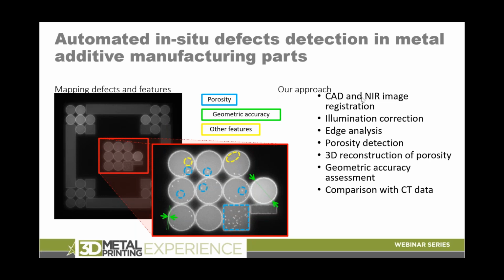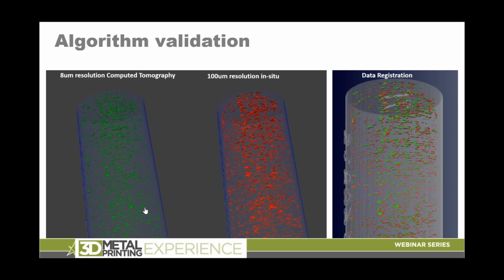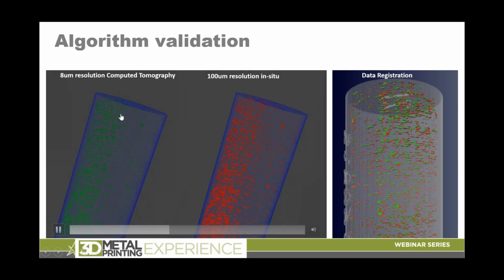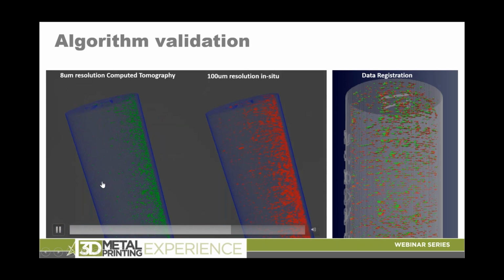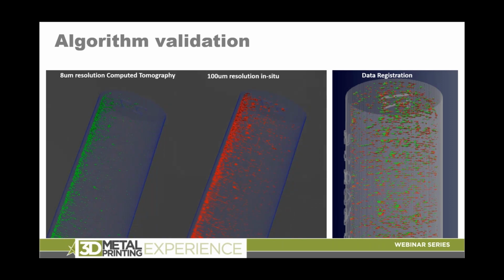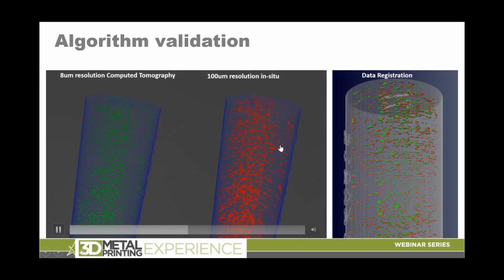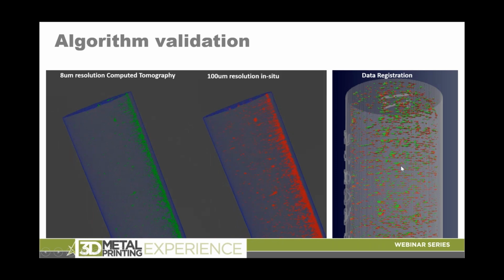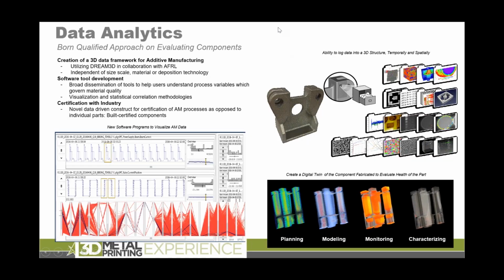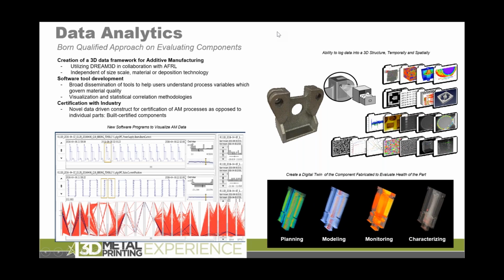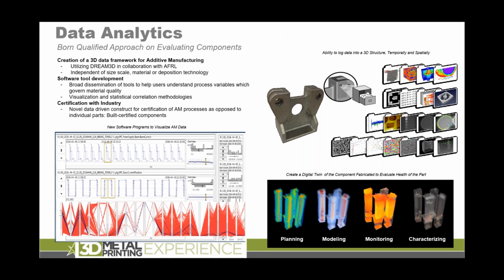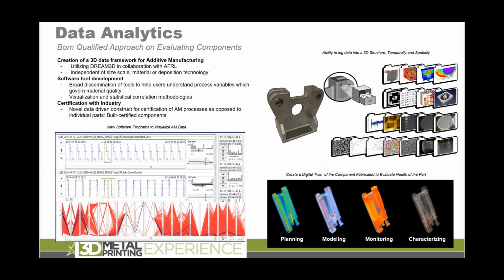We use that data to create a 3D reconstruction of the part, and then we compare that with CT data. On the left is the CT data, and then on the right is our 100 micron resolution in situ data. That's what we took as the part was printing, and then we use those two models to register the part and register our model as well, register our AI. Using this type of data gathering, we can gather a lot of information about the part itself. This goes to that digital twin.